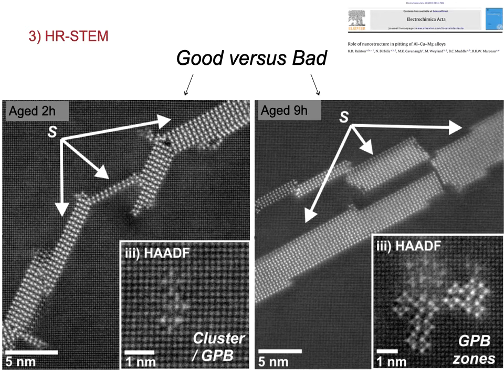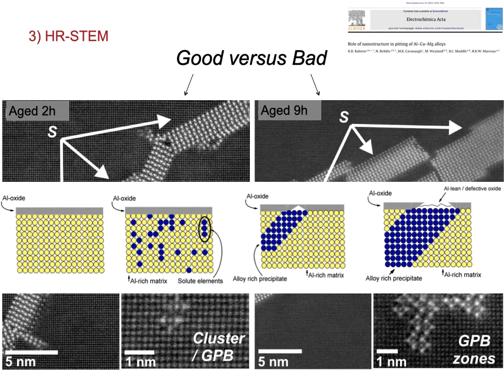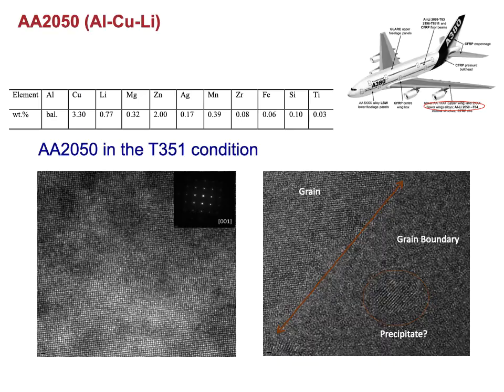An attempt to reveal this phenomenology is given by this schematic as well, where it's proposed that a protective surface oxide may be able to bridge precipitates, provided they are less than a critical size, which is around 5 nanometers or so. This study, I'm only giving you a short snippet of it, also included atom probe and other characterization as well.